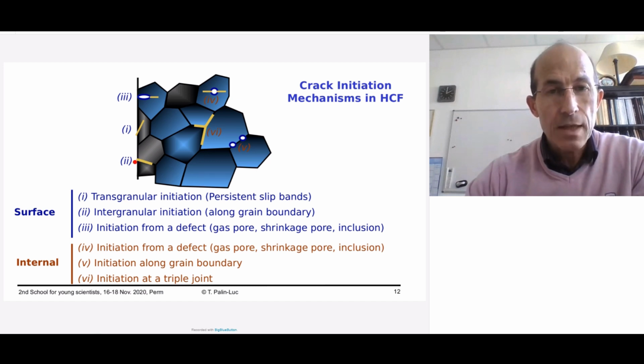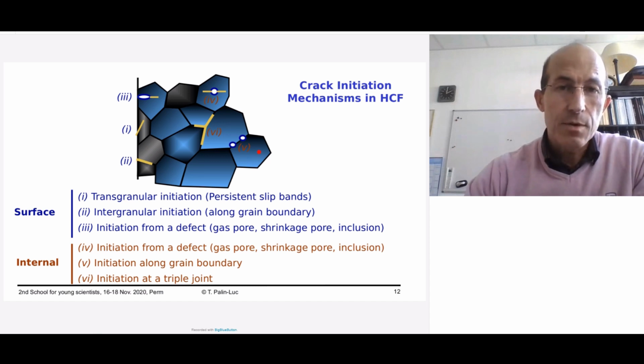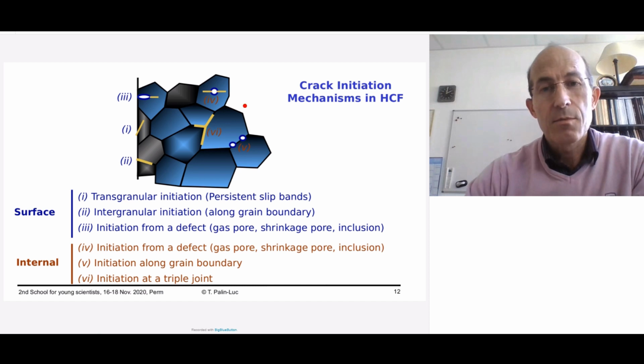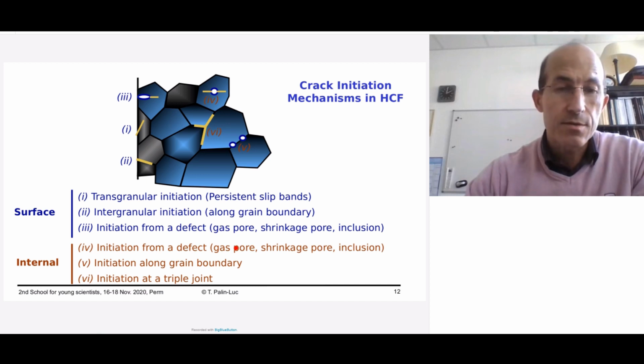And in some cases, it's also possible to observe internal crack initiations, even in low cycle fatigue or high cycle fatigue, but they are not very common in pure materials. They are common in industrial alloys because of defects. So again, the defects play an important role, like the pores, the shrinkage, and so on. One observes also initiation along a grain boundary with the presence of defects. And in some cases, but which are rare, we observe initiation of a crack at the triple joint.